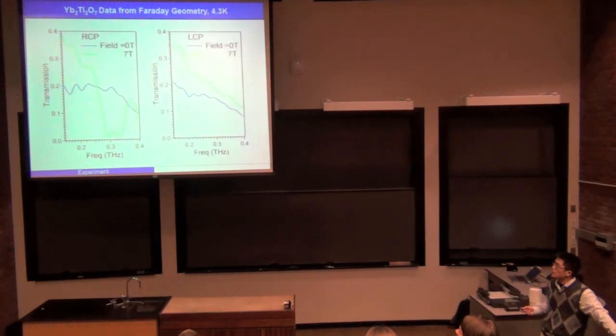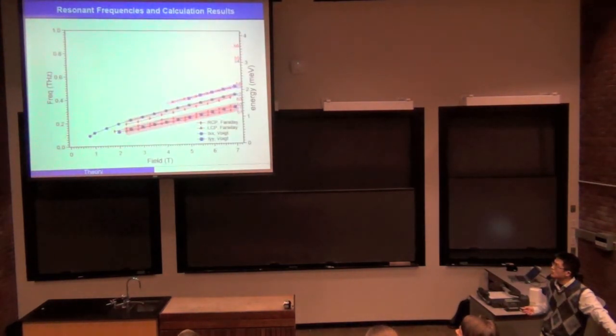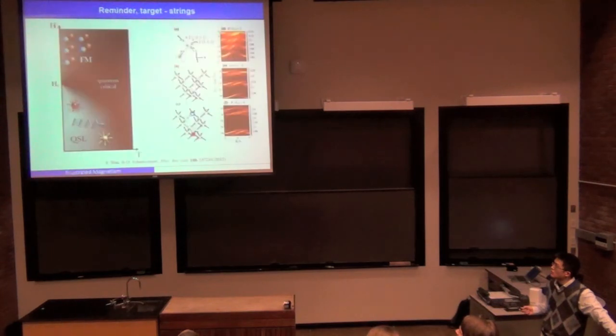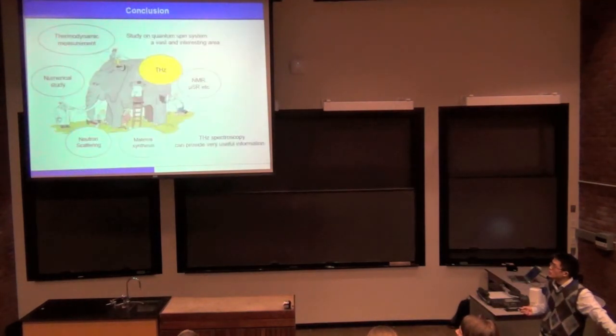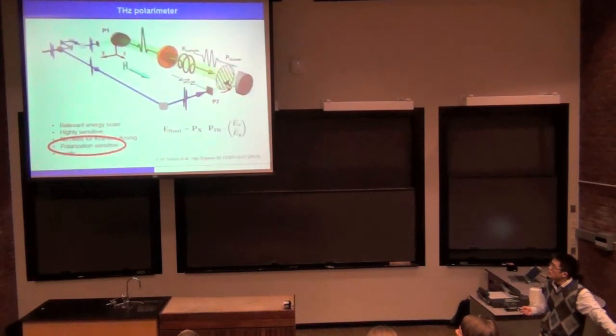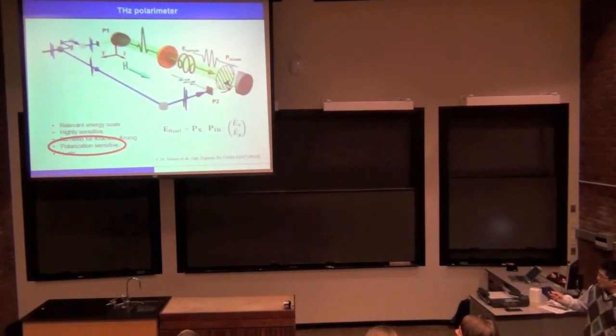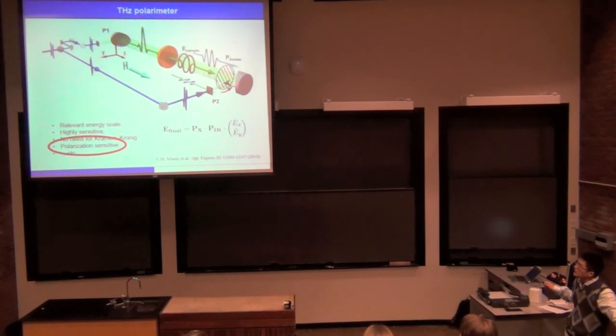So that's where, yeah, somewhere around here, right? So this is the Terahertz polarimeter. We call it polarization modulation. So here we have a polarizer, which is a Terahertz polarizer, just a wire grid polarizer, and then we spin it at a high frequency. And because a polarizer does not distinguish 0 and 180 degrees, naturally this polarizer will have a 2 omega component.